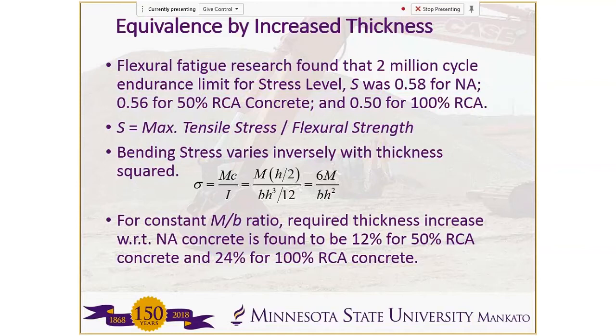So in one paper, we found that the stress level was 0.58 if you're using natural aggregates, and 0.56 for 50% RCA concrete, 0.5 for 100% RCA. And the stress level is just the maximum tensile stress that the pavement is going to feel, relative to the flexural strength of that pavement. From mechanics theory, we know that the bending stress varies inversely with the thickness squared. So if you assume a constant M over B ratio, where B is the width of the pavement, then you can find the theoretical required thickness increase if you want to achieve similar flexural fatigue life.